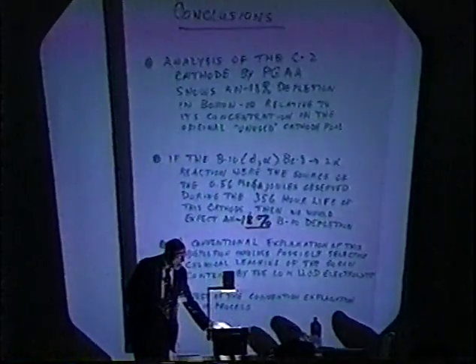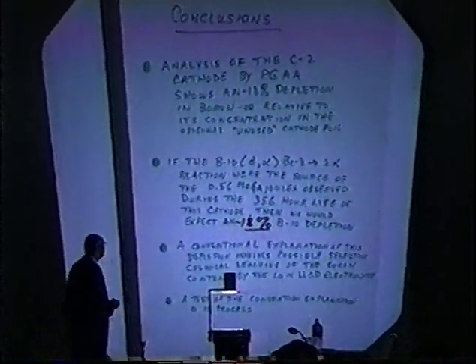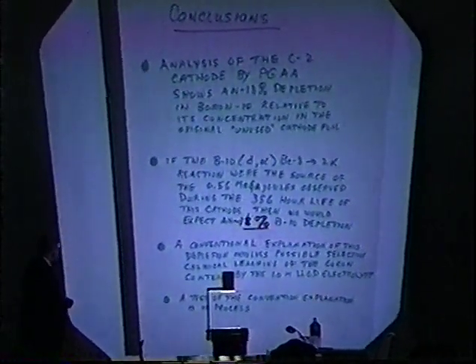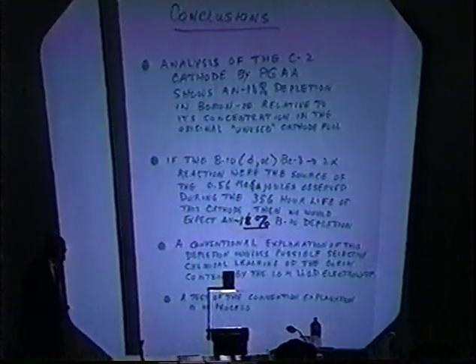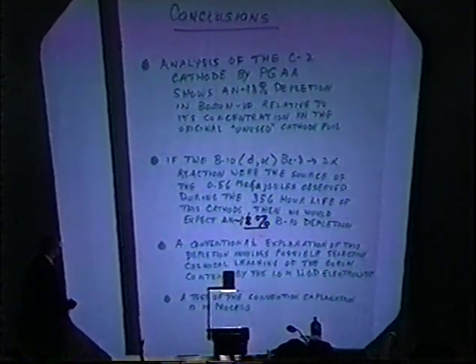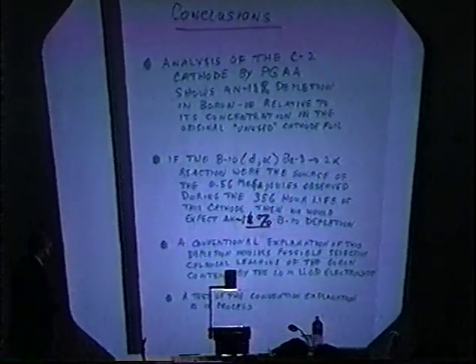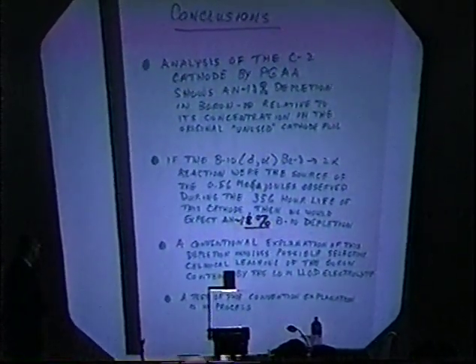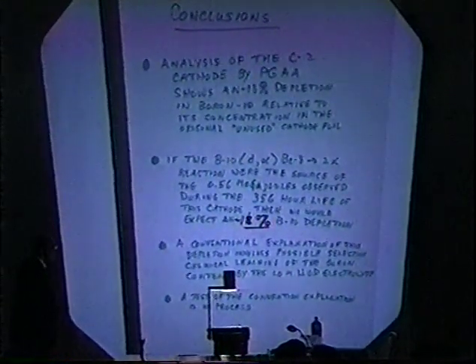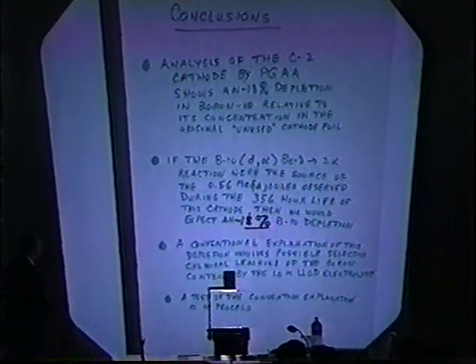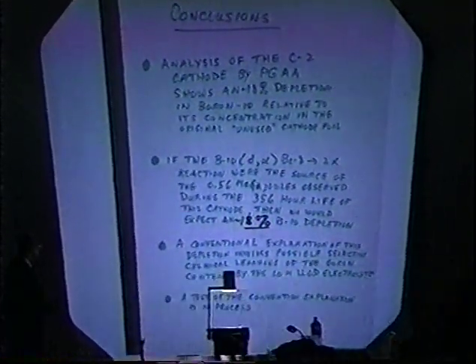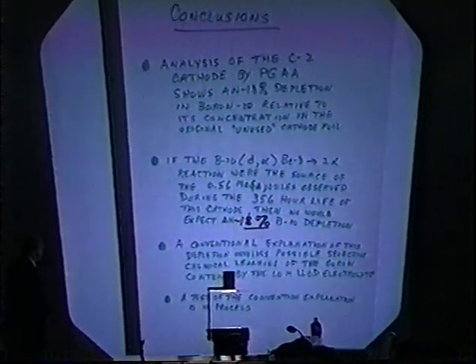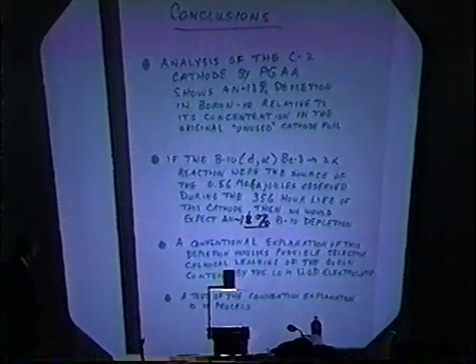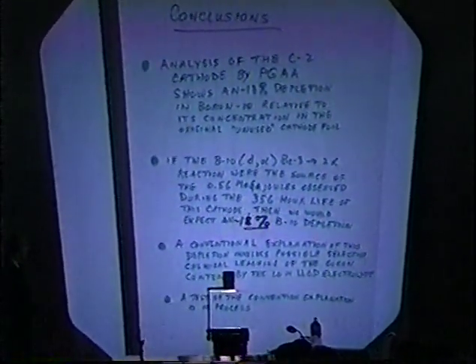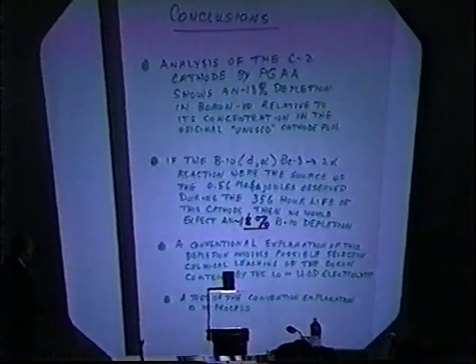Now, conclusions. The analysis of the C2 cathode by PGAA, that's prompt gamma activation analysis by thermal neutron capture, shows about an 18% depletion in boron 10 relative to its concentration in the original unused cathode foil, which, by the way, was about 1 mil or 25 microns thick. If the boron 10 D-alpha reaction to make beryllium 8 going on to 2 more heliums reaction were the source of the 0.56 megajoules observed during the 356-hour life of this cathode, then guess what? We would expect about an 18% boron depletion.